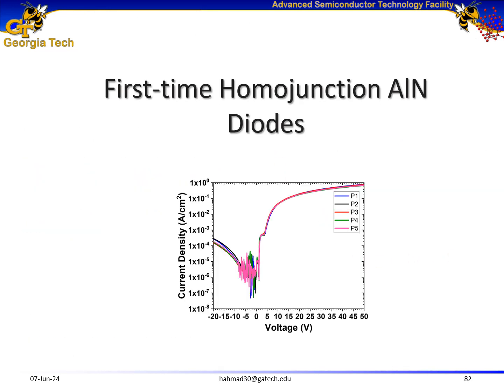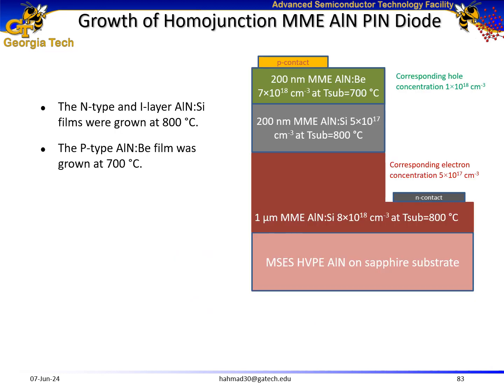So now the stage was set to perform the final study, which is first time homojunction aluminum nitride diodes. This slide shows the layer structure diagram of these diodes, where I grew the N-type aluminum nitride and the I-type aluminum nitride, which are silicon doped at 800 degrees C substrate temperature, and I grew the P-type beryllium doped aluminum nitride at a substrate temperature of 700 degrees C.